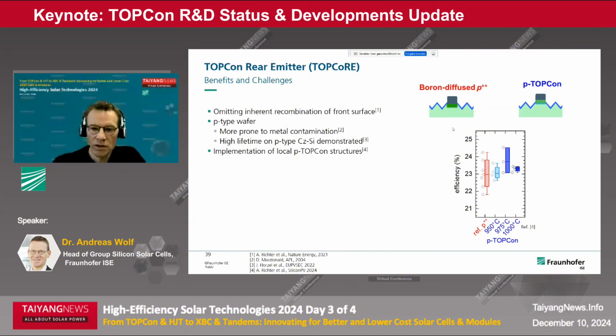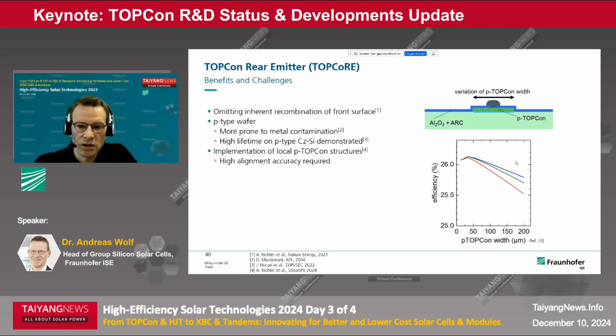Of course, these cell structures should feature local TOPCon structures on the front side. We were able to implement this on small area cells already. One challenge here is the alignment of the structures. Of course, you need very narrow local TOPCon fingers to minimize the parasitic absorption. And it's a question how this alignment requirement can be met by industrial production conditions.